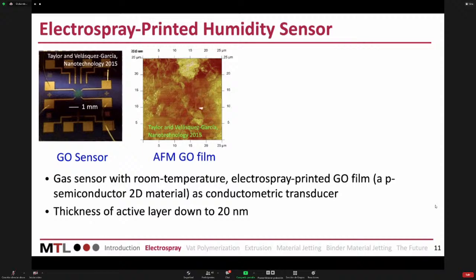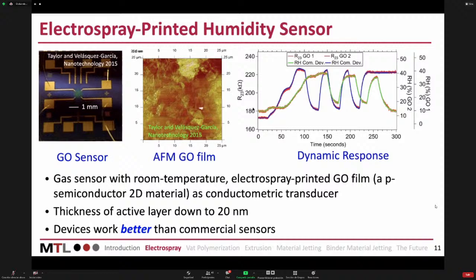But I think what is really important is that even though it's a low-cost technology, you can make something that is actually useful. And what you see here is the data of how the resistance changes versus time. So it's a dynamic response. We put the sensor in an environmental chamber that allows us to change the humidity, and you can relate the electrical resistance change to the humidity that you have there, okay?